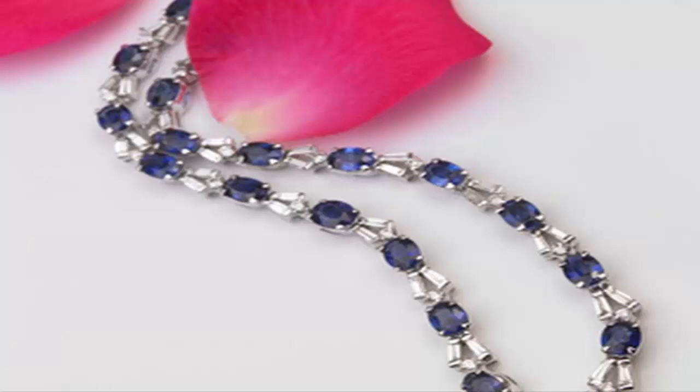In a 1993 study published in the journal Gems and Gemology, authors John L. Emmett and Troy Douthit found that heat treating sapphires in an oxidizing environment created yellow colors. Cooking sapphires in a reducing environment, such as that of a combustion furnace, created blue colors.